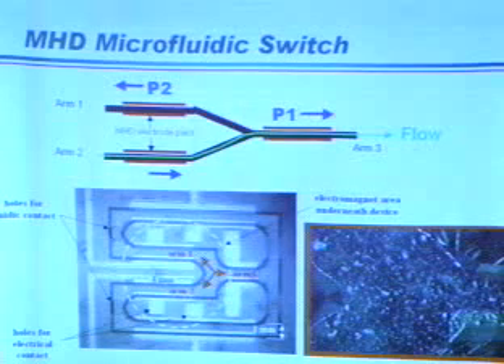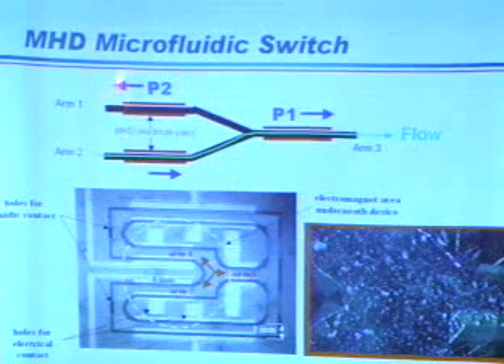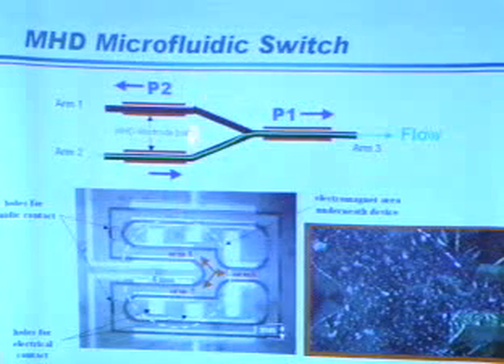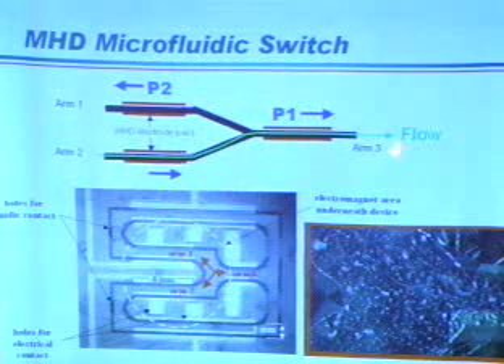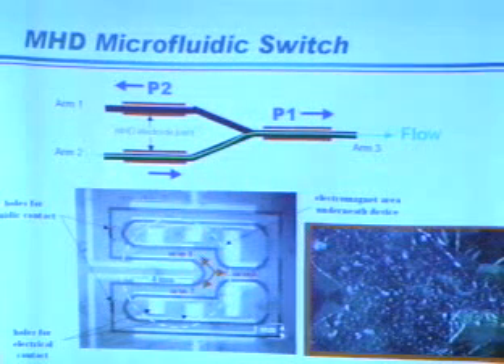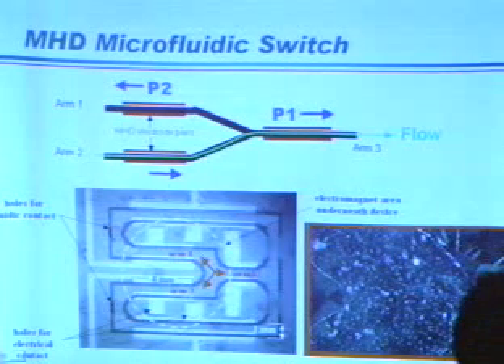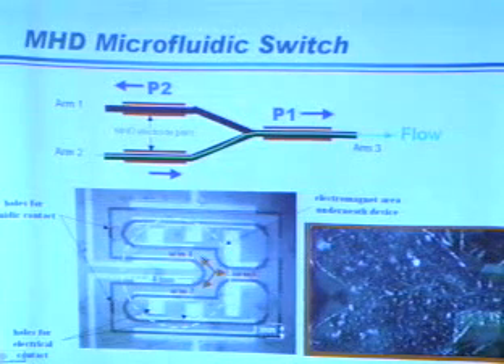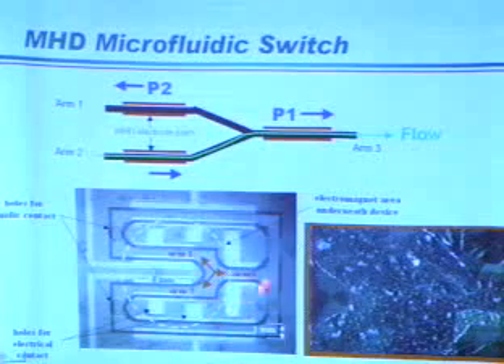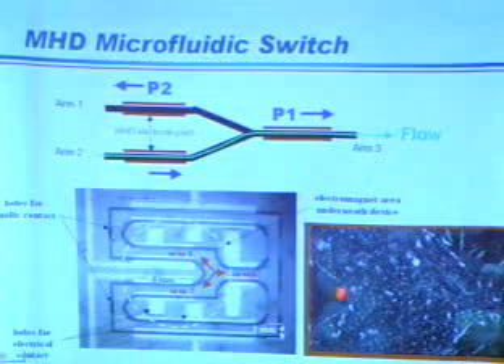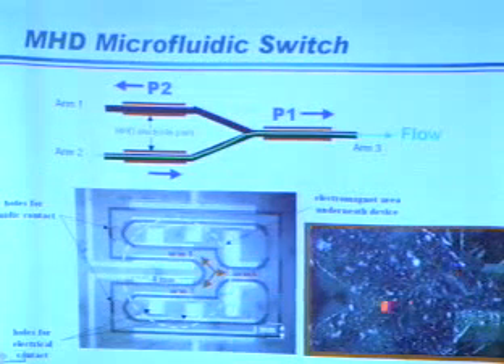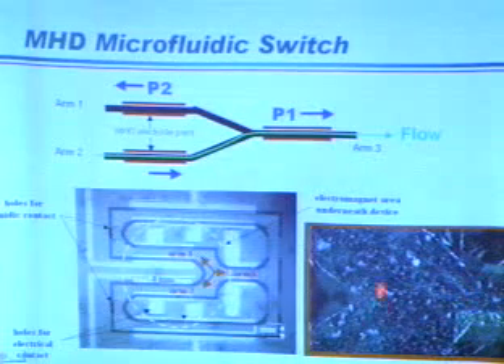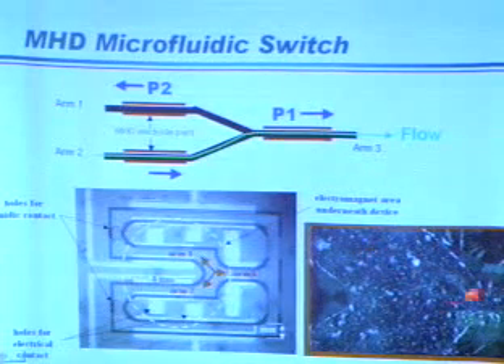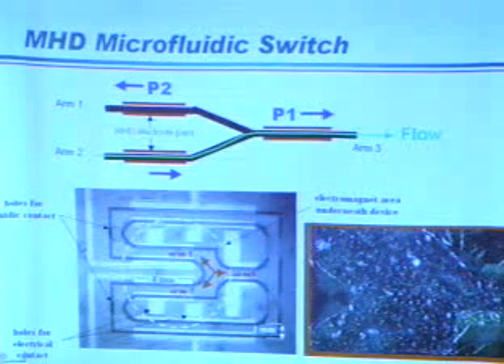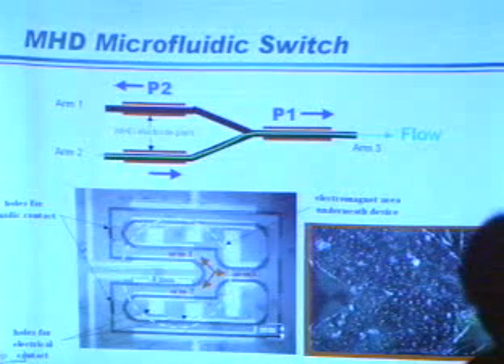And the same thing, of course, if you apply counter pressure on the top here, you can switch back and forth instantly again from arm 1, arm 2 into arm 3. And this is not the best example because we ideally need the dimensions to be much smaller, because here you have a swirling motion. Basically, viscosity allows it to swirl around. So the switching effect is not as good because you have mixing at the junction. But it shows you the phenomena.